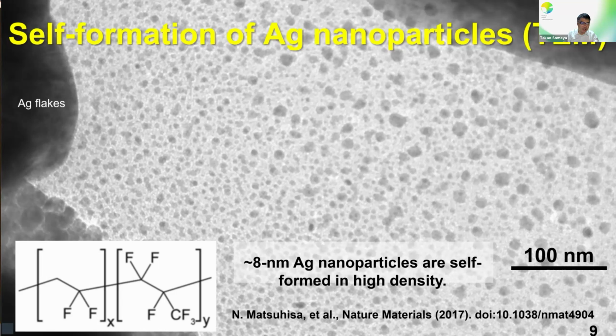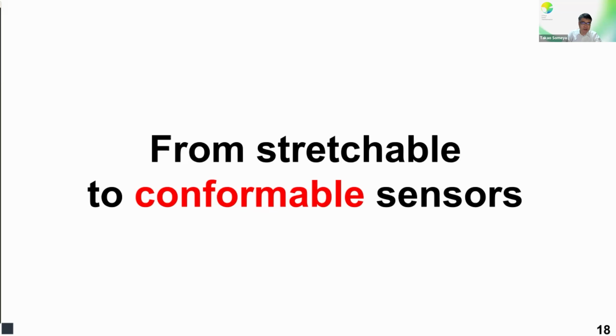Although we didn't add the silver nanoparticle intentionally. So as I mentioned, we simply utilize the silver flake with 2 to 3 micron, but silver nanoparticle is naturally formed. And you may see this is a magic of nanotechnology that allowed us to obtain the high conductivity and high stretchability simultaneously because of the efficient percolation conduction. And then I move to the next topic, that is conformable sensors.